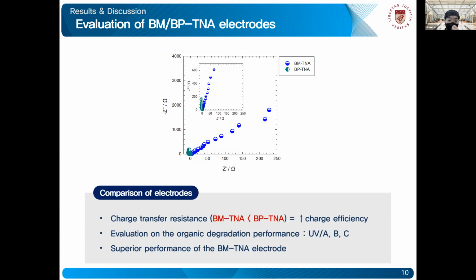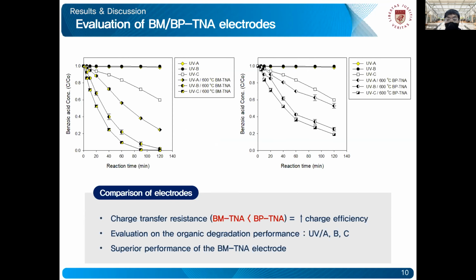To confirm the electrochemical properties of the BP and BM TNA electrodes, we conducted EIS analysis. The analysis confirmed a reduction in the charge transfer resistance for the BMTNA electrode, which naturally led to improved charge efficiency. Subsequently, the organic degradation potential of the two electrodes was evaluated using benzoic acid as a model substrate under three different light sources as previously introduced. As you can see from the results, the PEC system showed far superior performance for the BMTNA electrode under all light sources.